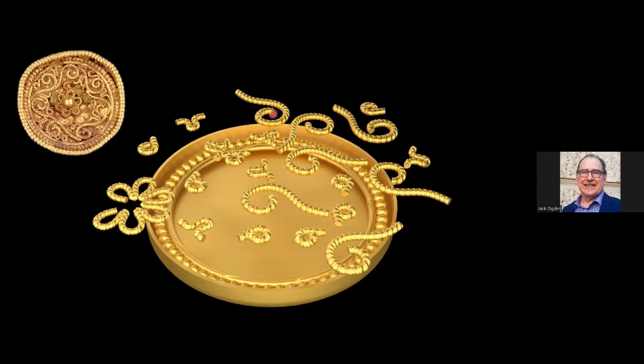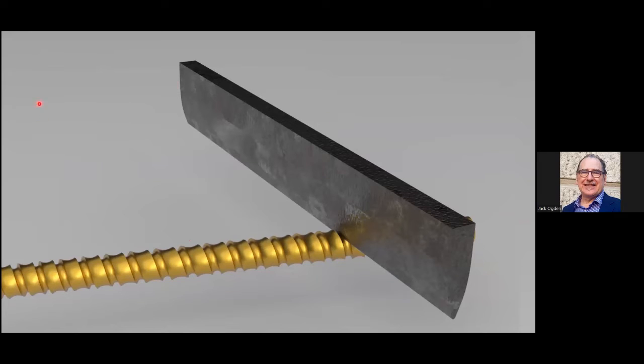Now, at first glance, this looks like a little more beaded wire, but it isn't. It's a particular type of beaded wire. It's what they call spiral beaded wire. That sounds a bit technical, but it was generally used for narrower diameter wires when it was a bit too fiddly to make normal beaded wire. So what they did, they rolled a wire under a single edge, but at an angle. So it's almost like a screw thread along the wire.